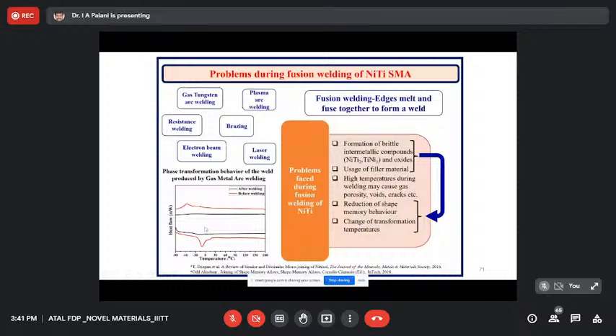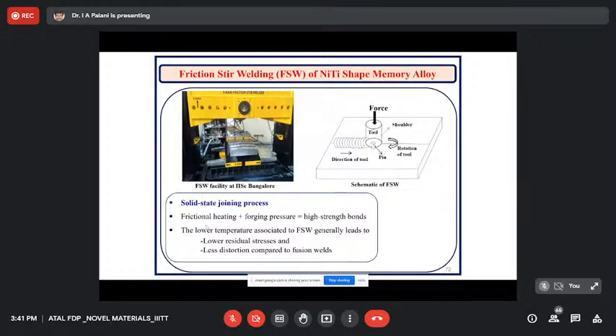A wide variety of people have attempted this, using gas welding, resistance welding, electron beam welding, plasma arc welding, laser welding, etc. Here we are talking about friction stir welding. In friction stir welding, there is frictional heating plus a forging pressure applied to get a higher strength bond, and the lower temperature associated with friction stir welding will lead to a lower residual stress as well as less distortion.